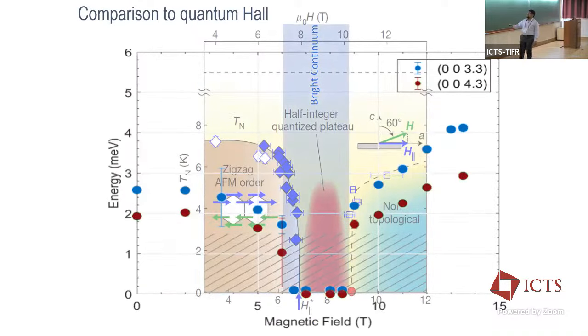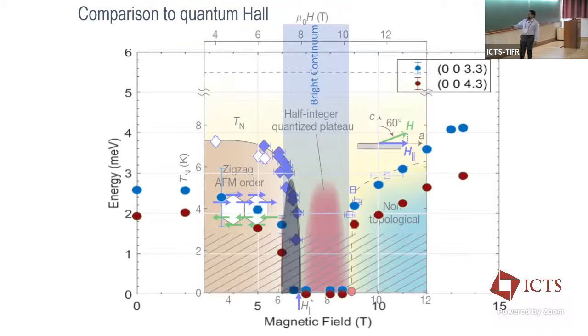And if we superpose that on top of Kasahara's phase diagram, what we find is that that's your zigzag phase right there, and that's where he expects a half-quantized thermal Hall plateau. So that tells you that you have one ordered phase here, a second ordered phase here, then the half-quantized plateau, and then you have some kind of a third ordered phase at high fields.